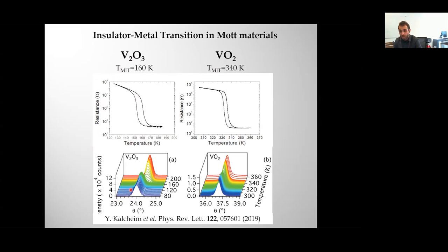So these that you have here, these are X-ray diffraction, two theta scans at different temperatures. Blue is colder, red is hotter for V2O3 and for VO2. And you can see that at the transition temperature, you have a shift in the Bragg peak. So there is this structural transition that is happening together with the electronic transition. And there has been a lot of debate. Some people were saying that these transitions actually don't happen together, but are decoupled. Somehow you first have a transition from metal to insulator, and then a few kelvins lower in temperature, the structural transition happens. We did careful measurements, you can find them in this paper, and we track them, and we see that no, these two transitions are really well coupled, and they happen at the same time.